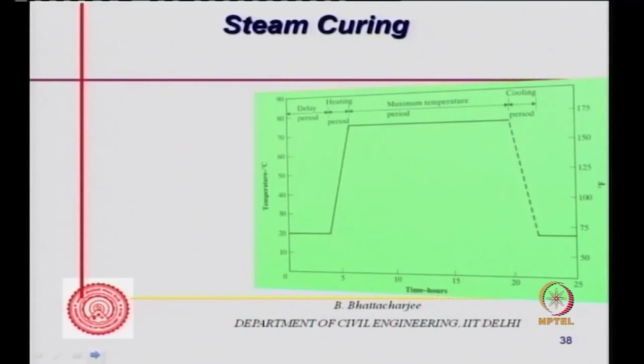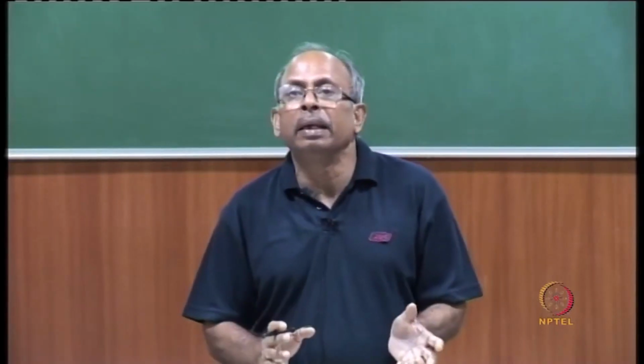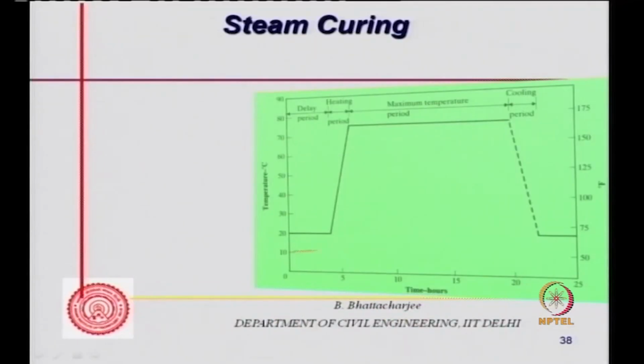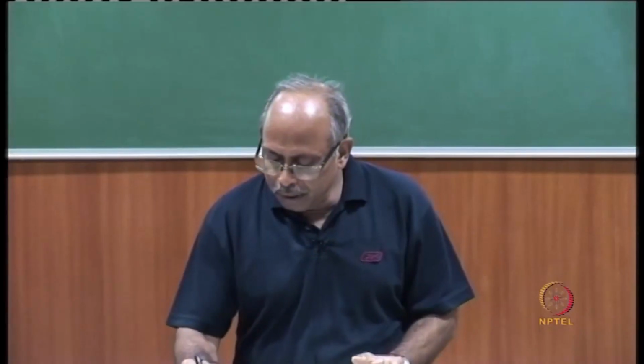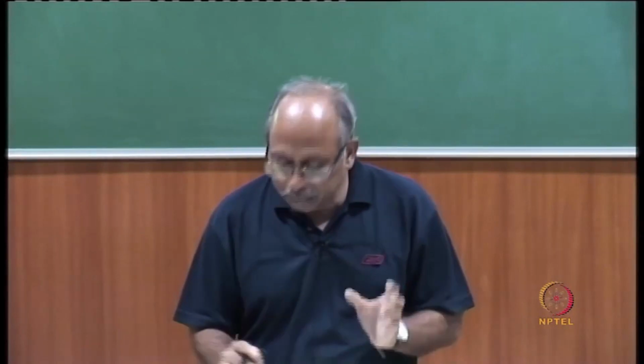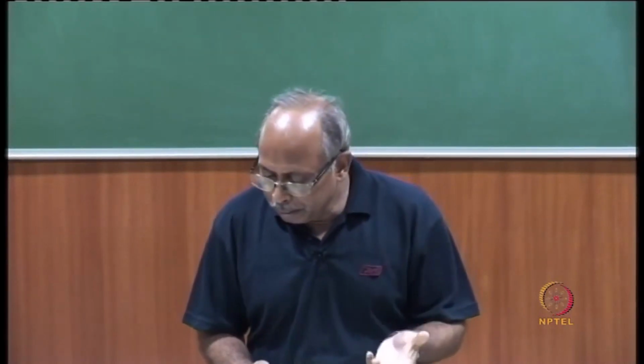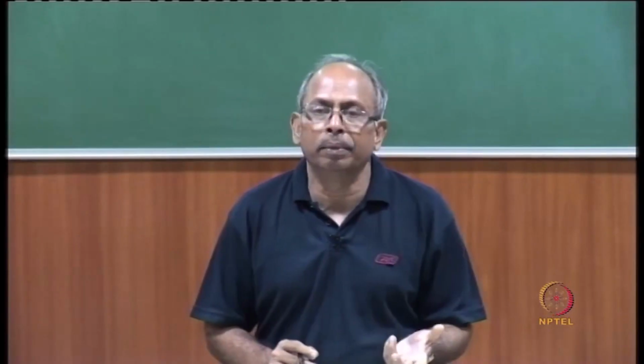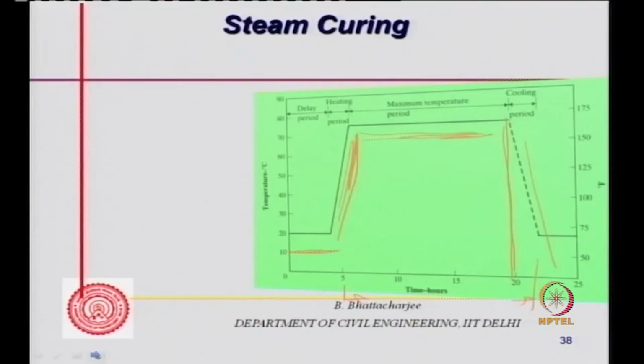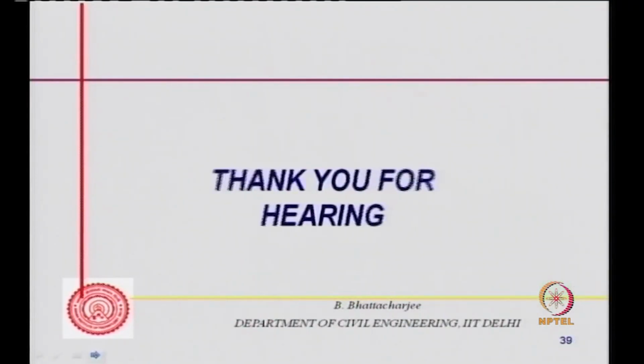So what you do is you don't apply it immediately, because then you don't get the strength gain. There is a delay period. Then there is a steam heating period: supply the steam and maintain that temperature, then cool it. If you do steam curing for about 13 to 15 hours, this is the kind of practice that we follow, and we get good strength. All right, so this is a typical steam curing cycle, used if you are trying to get early strength.